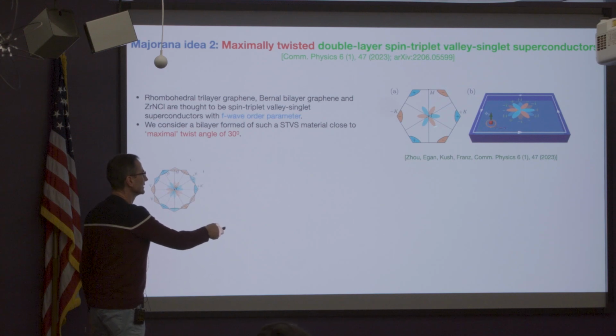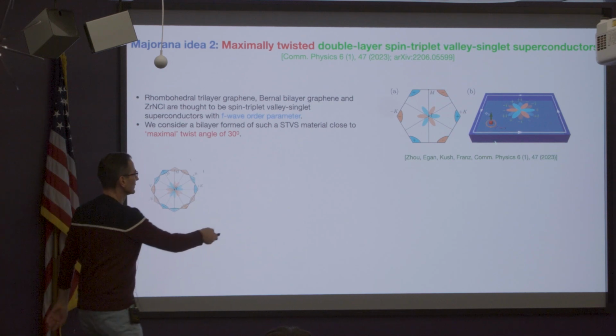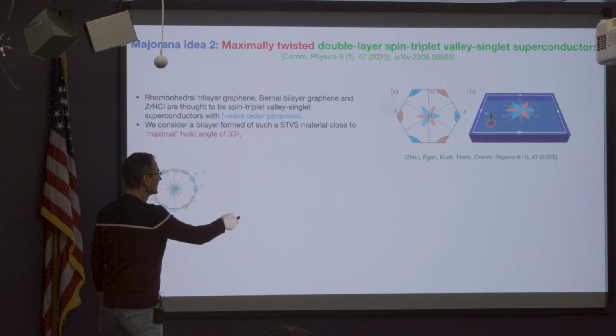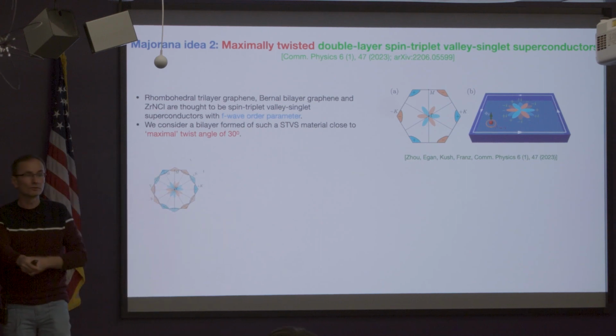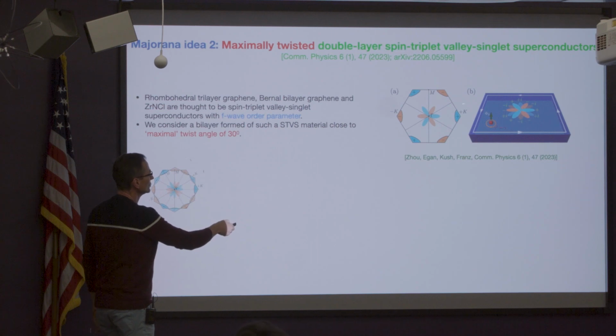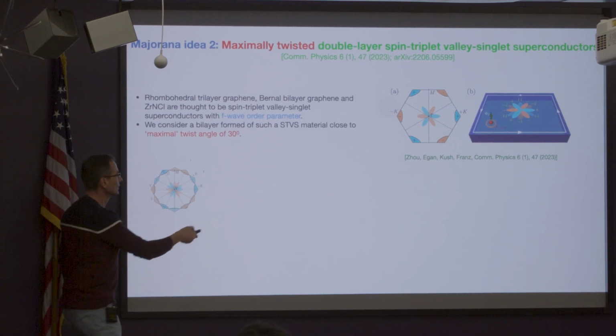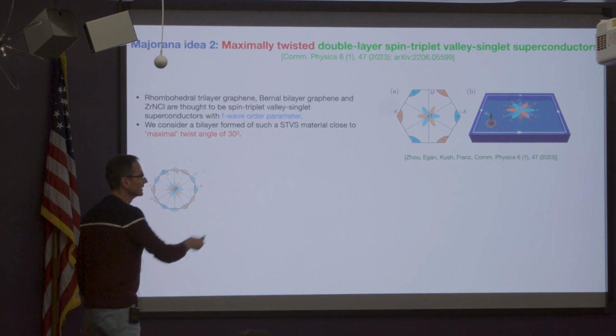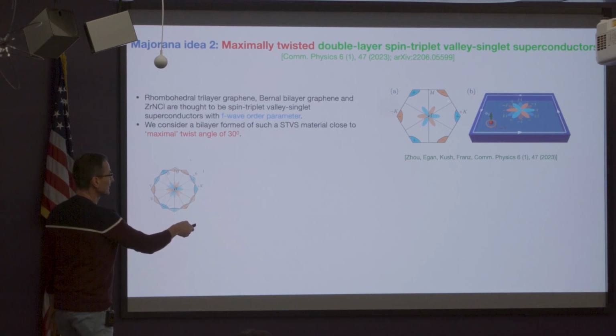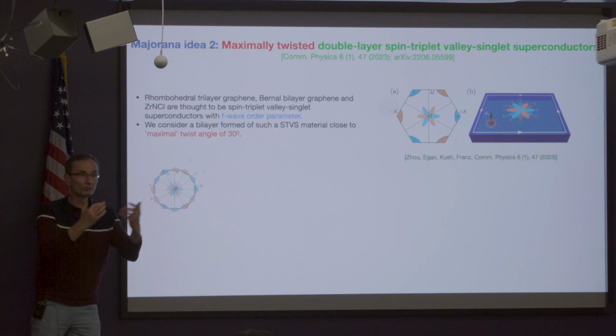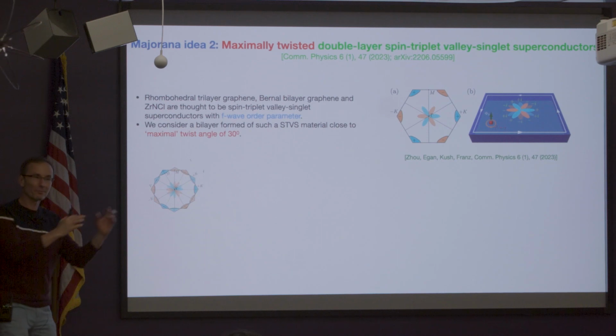So here, this is not really physical. What my postdoc plotted in the center of the Brillouin zone is not a Fermi surface, right? That's just a representation of the order parameter. Where the electrons reside is on these small corners of the Brillouin zone, and the coloration here is meant to encode the sign of the gap on that part of the Fermi surface. So you notice that the blue and orange are not really touching or even close to one another. The order parameter technically goes through 0 at this line, but there are no electrons that are affected by that. However, here, these two Fermi surfaces are actually touching, and that's why these electrons have to decide whether to have a positive or negative order parameter. They cannot have both, right? So that's where the frustration comes in.